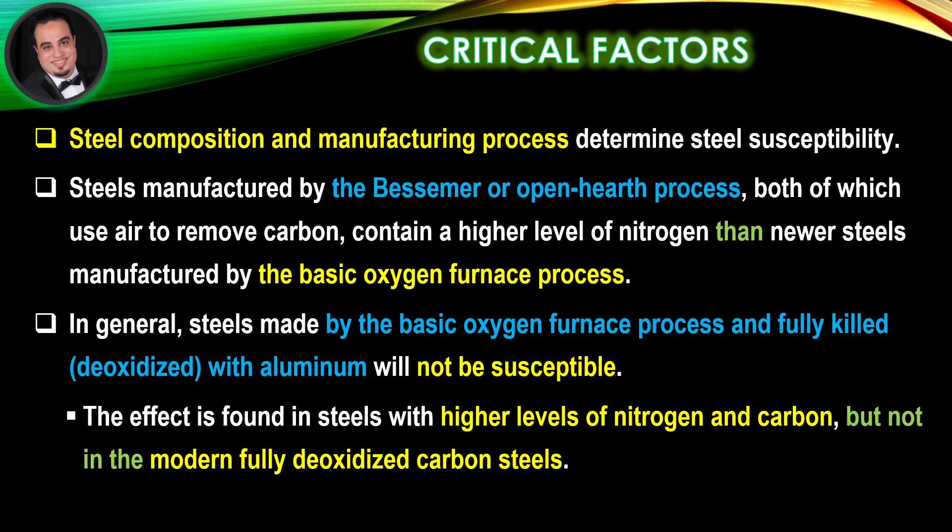Critical factors: steel composition and manufacturing process determine steel susceptibility. Steels manufactured by the Bessemer or Open Hearth process, both of which use air to remove carbon, contain a higher level of nitrogen than newer steels manufactured by the basic oxygen furnace process.